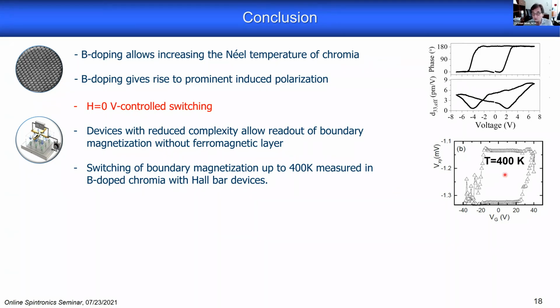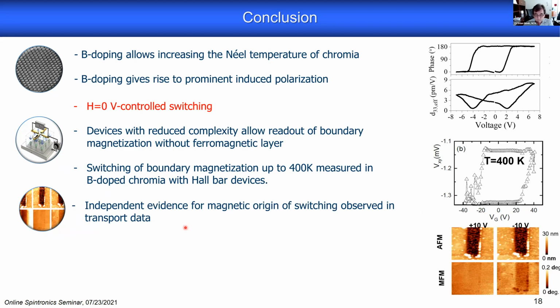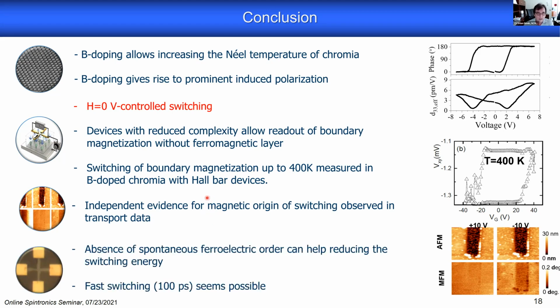And this can also be done up to 400 Kelvin. Here is actually a data point at 400 Kelvin, not so beautiful, but at least there still is an effect. And I showed you independent evidence that this is indeed magnetic in origin. And a few words about the switching speed. So there's a theoretical estimate about the switching speed.